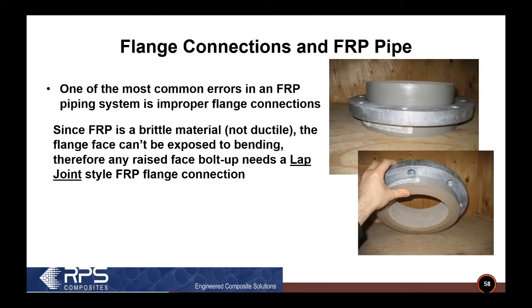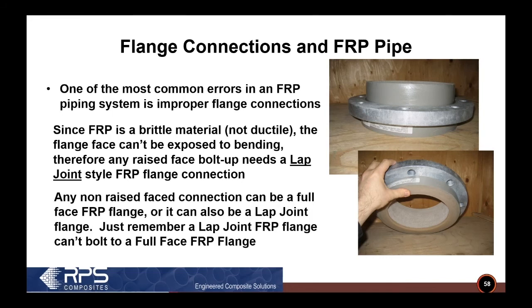And you can see by my thumb there, it's only the FRP hub that's going to press against the lining, and a steel ring slips on behind, and that's where the pressure is put evenly on the FRP. There's not the same kind of bending torque on the FRP, and that's how you need to connect any type of raised face, is to use a lap joint style FRP flange.